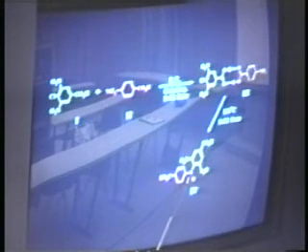So the other polymorph of 3 is still a diacid co-crystal. When that polymorph is heated, however, what happens is this new compound forms. So compound number 4 forms, which is an entirely new molecule. And if you look carefully at it, what you formed is a new nitrogen-carbon bond, and the chlorine has been displaced. So we've done a nucleophilic aromatic substitution reaction in the solid state. This is a 3-step solid state reaction. This molecule will form quite easily in solution from those components.